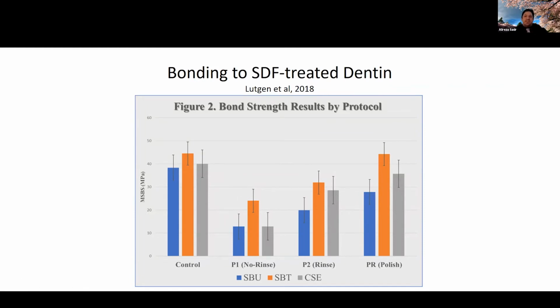Even if you're leaving the SDF, I highly recommend that you rinse off the SDF after 2 to 3 minutes, okay? Wait 2 to 3 minutes and rinse it off, just don't leave it there. It's also because of the potential of penetration of the silver and fluoride ions into the pulp, right? So you wanna rinse it off.